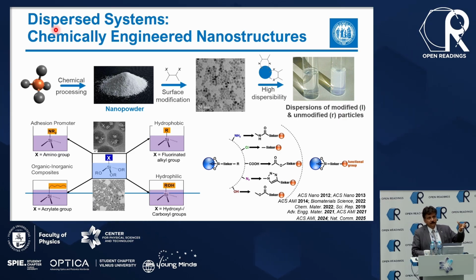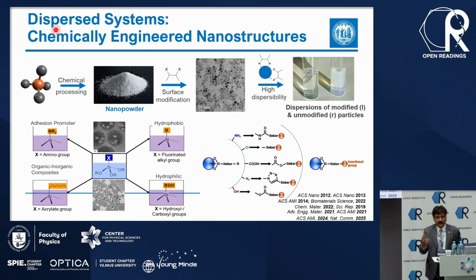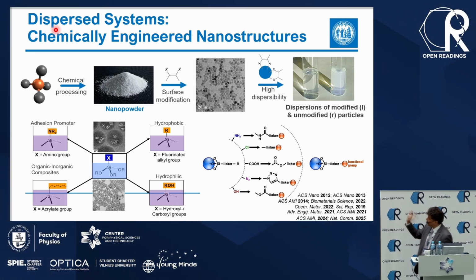If you take a ceramic powder and put it into solution, it's not going to work because the solid will just settle down, right? So you have to make it tractable by creating a surface functionality. And this was one of our first patents on how you modify a solid with small molecule conjugation. If you have molecules which have two functionalities, one side conjugates on the particle, on the solid, and the other side is open for a matrix, so you can put them into a polymer and polymerize them. This is called small molecule surface modification, or on-solid chemistry. So basically, it's conjugation chemistry on solids.